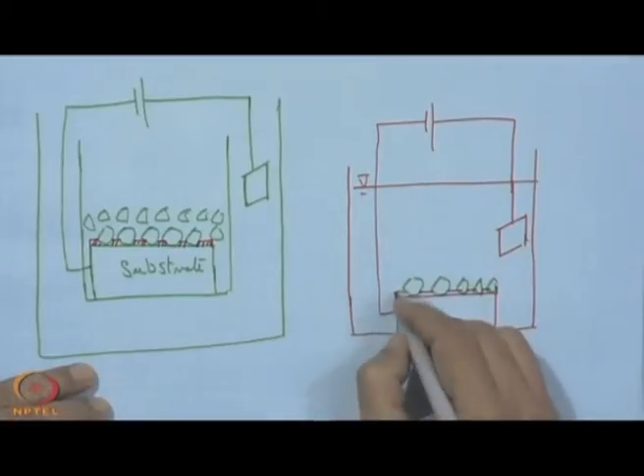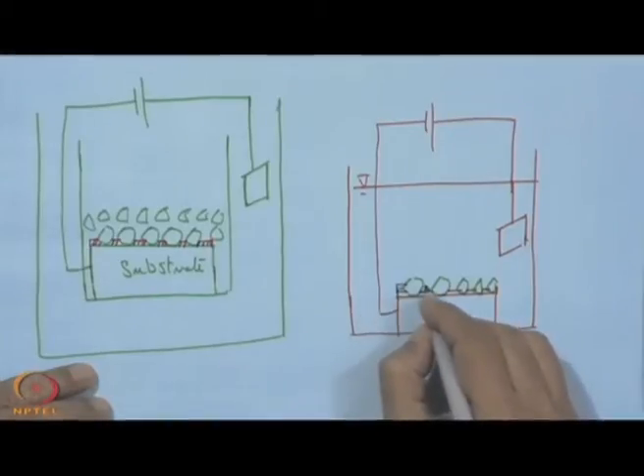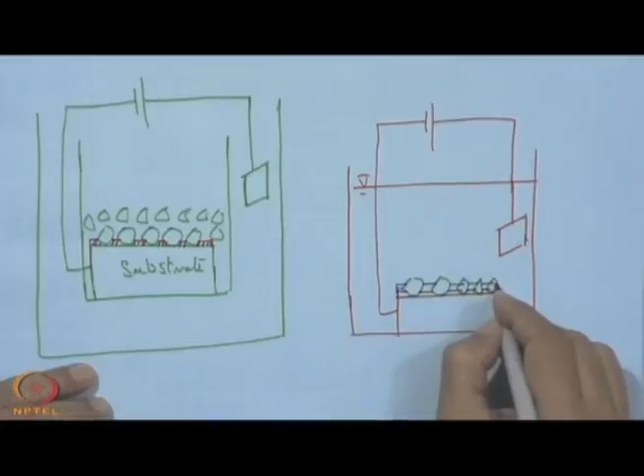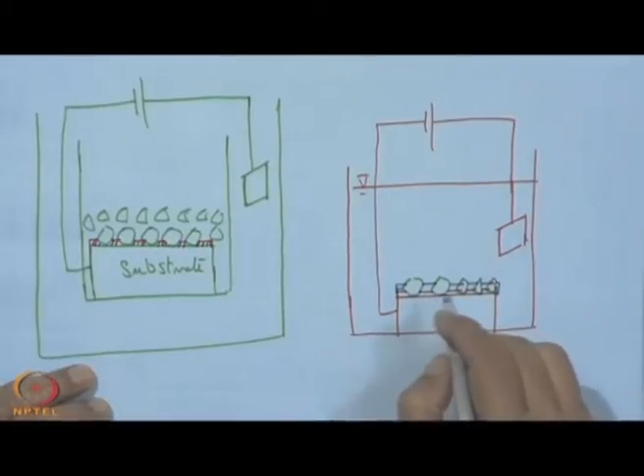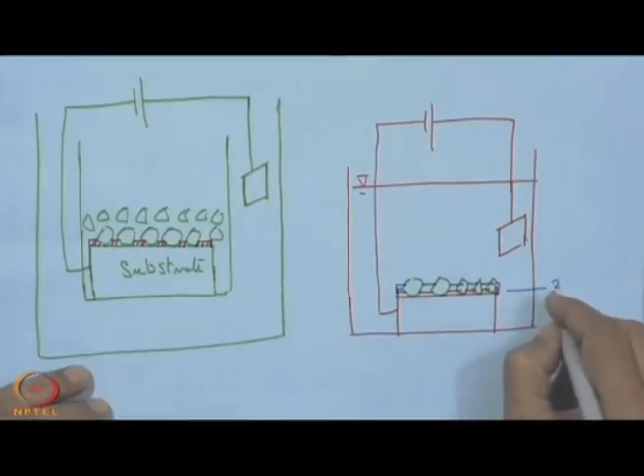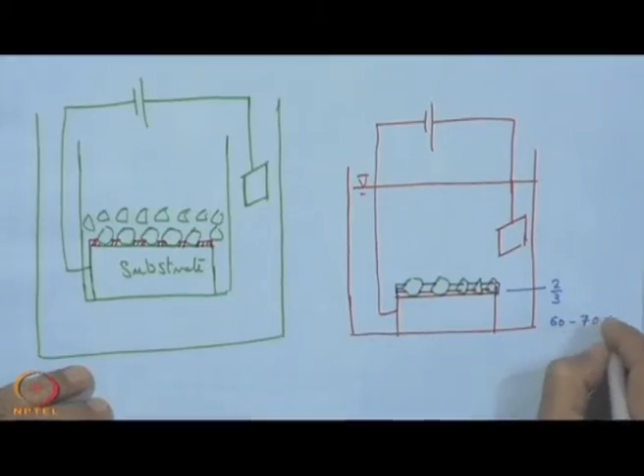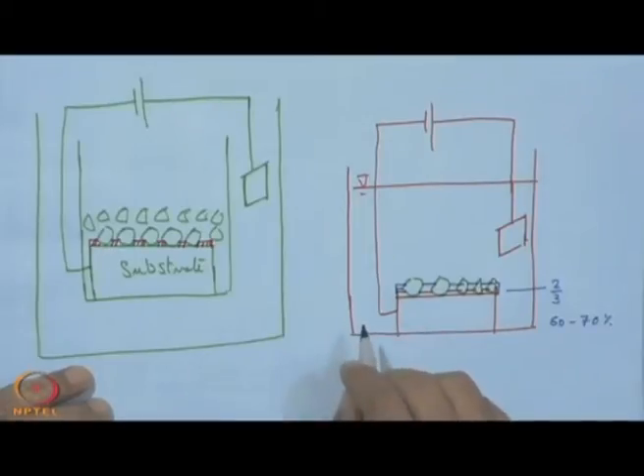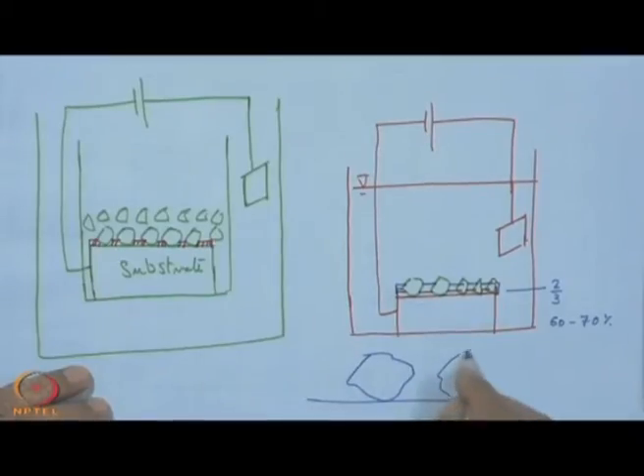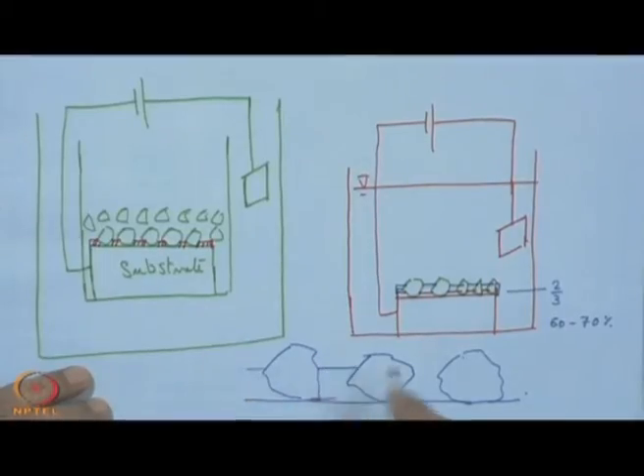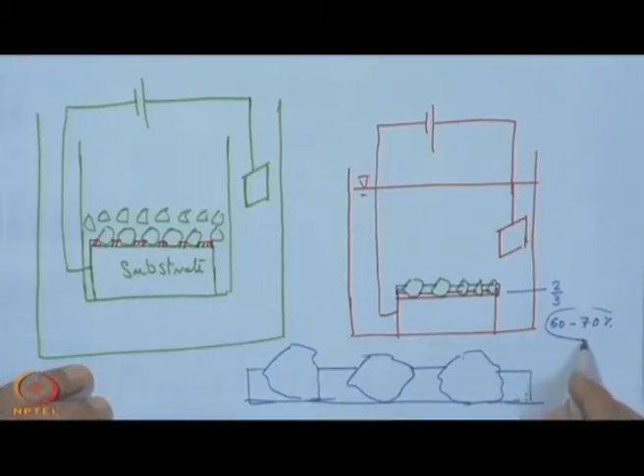So, this is actually the actual plating, and it will grow, and it depends upon the level to which it has to be covered, say maybe it is 2/3 of the grit height, or say between 60 to 70% of the crystal height that we can cover. So, from this concept of wedge, if we consider these grits as the wedge, we can see at least more than 50% need to be covered to have proper wedge action. So, it should be obviously around 60-70% of the crystal that is covered.